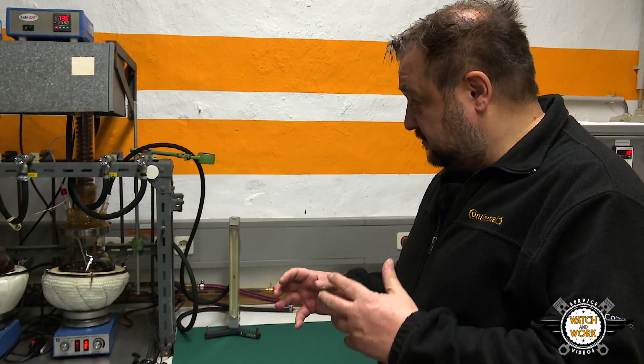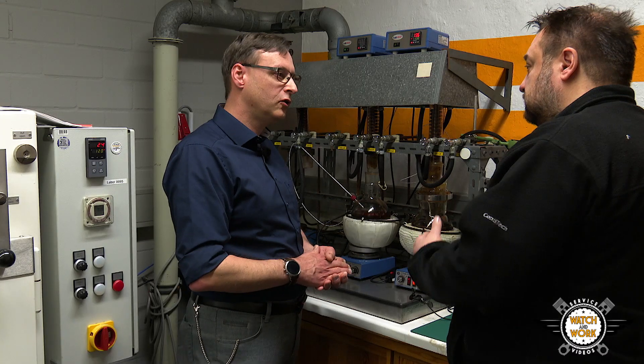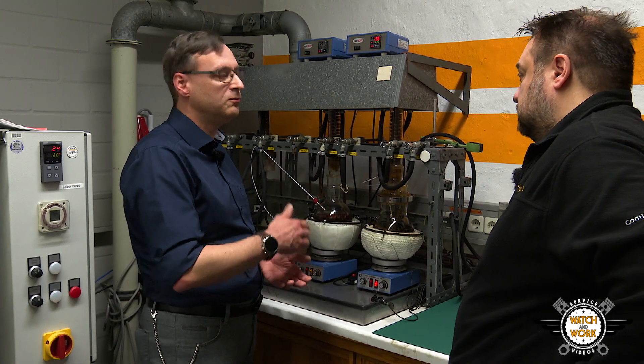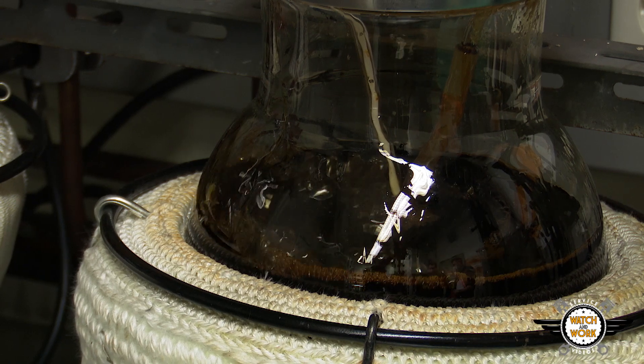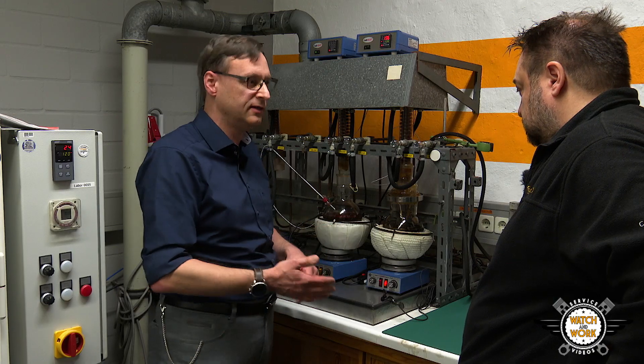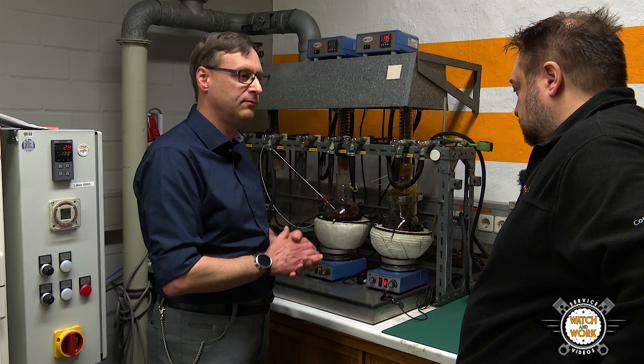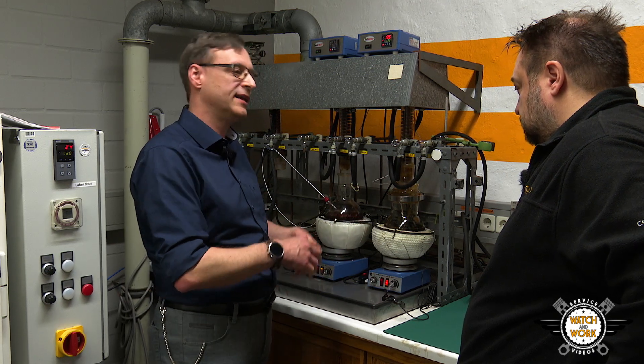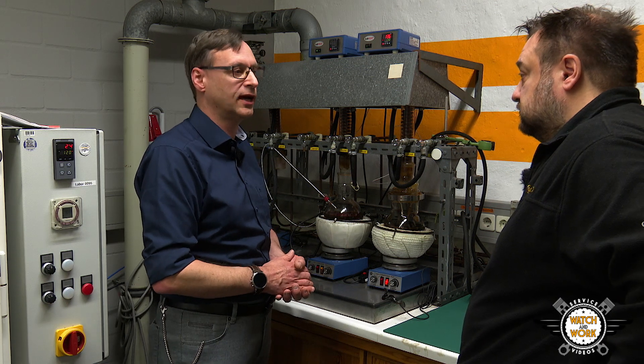And this is where you test all sorts of different fluids found in oil, fluids that can get into oil, as well as all kinds of different oils. We have created several hundred mixtures of oils with acid, with used oil, with soot and with combustion residue as our chemical media, which are then heated here and have the belts placed into them. Afterwards we test whether the belt is still 100% resistant and has not suffered any adverse effects.